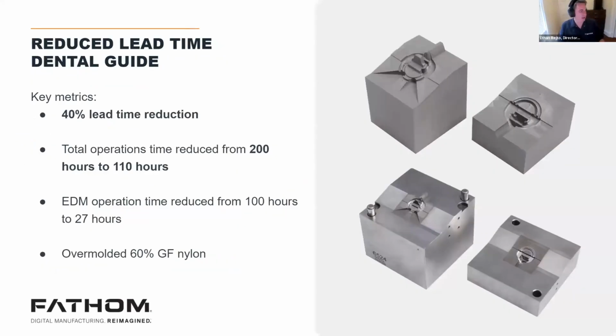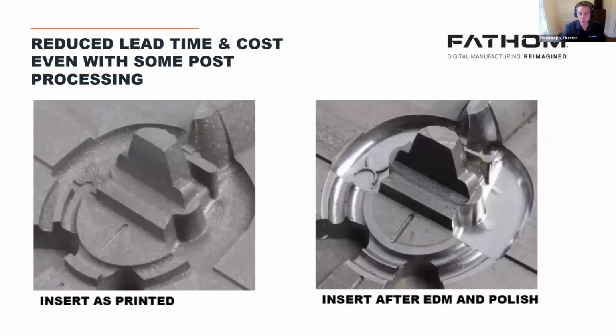A good example of this is this application with Fathom, two relatively small inserts that they are putting into a bigger block. This is actually an overmold application for a dental application. Printing here, they saw a 40% lead time reduction. They've reduced operations from 200 hours down to 110. But the reason I'm including this example now is actually because they still had to do quite a bit of EDM work, about 30 hours of EDM work here. You can see some of those features that are in here that are just too small for us to print and machine today.